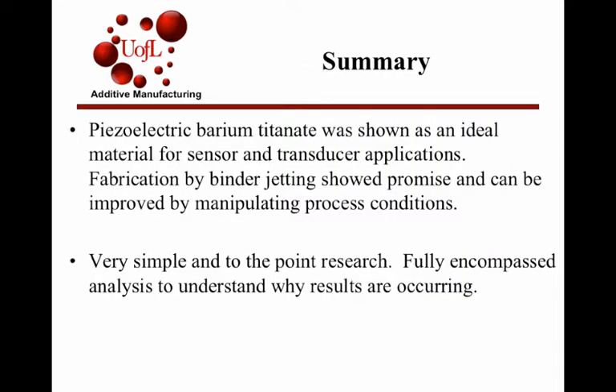In summary, the study did prove that barium titanate is a very good piezoelectric material, and it shows a lot of potential for the additive manufacturing side because it was very easy to print. They didn't give any graphs or anything, but basically they used digital calipers to measure the geometry. They didn't have a lot of variance in deformation of the part from different sintering temperatures. They pretty much got a very steady size of the part. The only thing that was varied was the density and the properties. So it looks very good for the additive manufacturing side. Very easy to print, not a hard process at all.